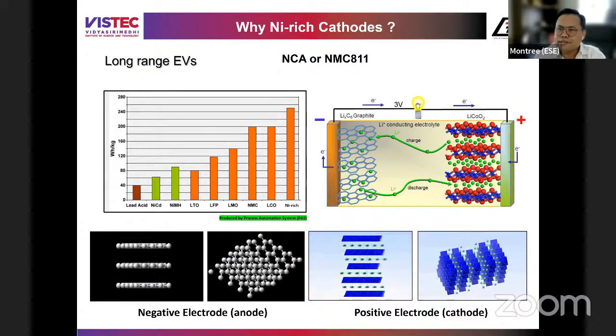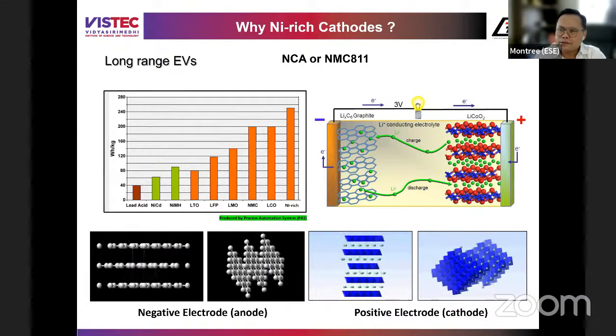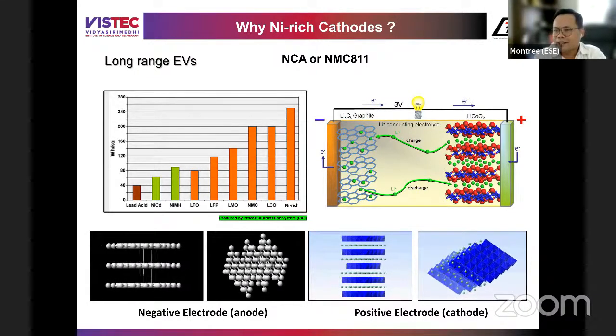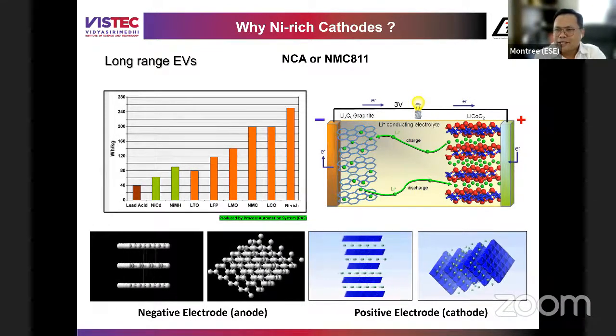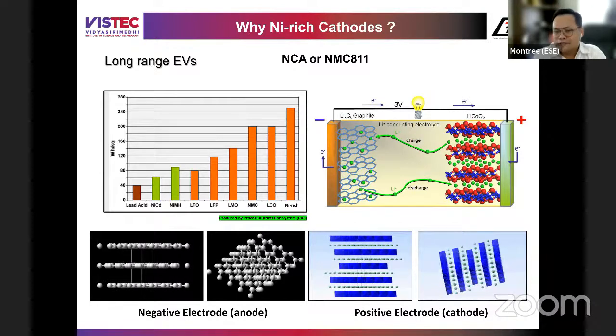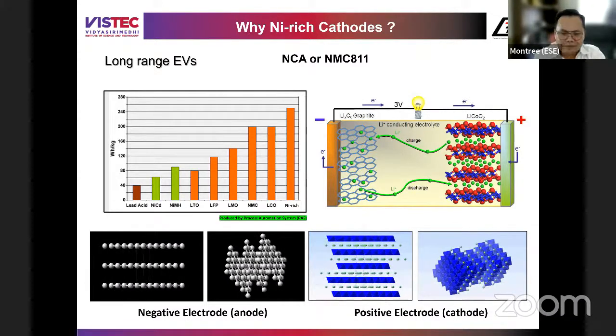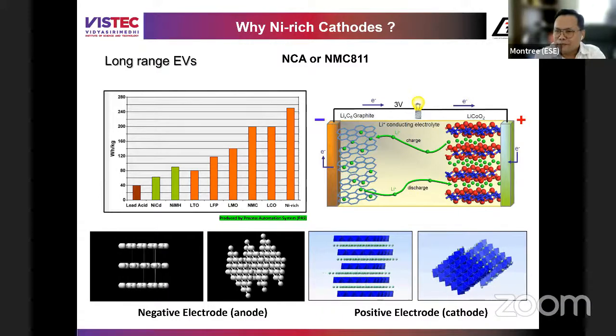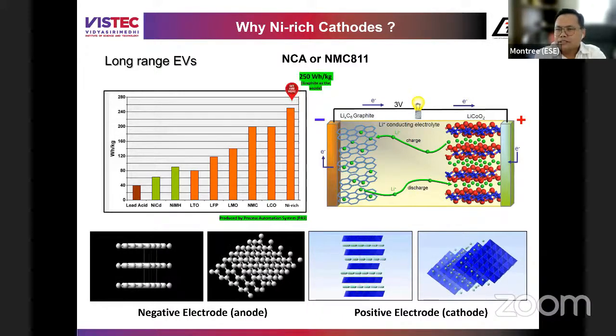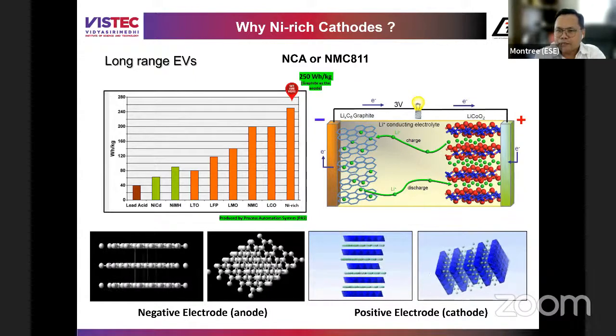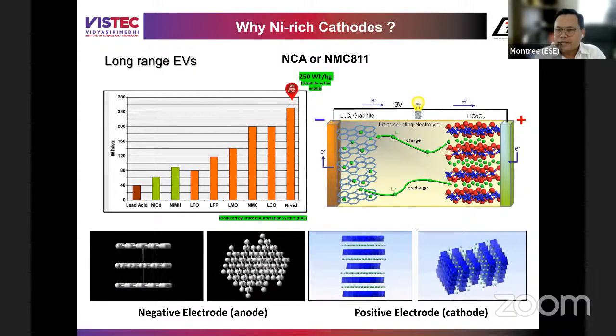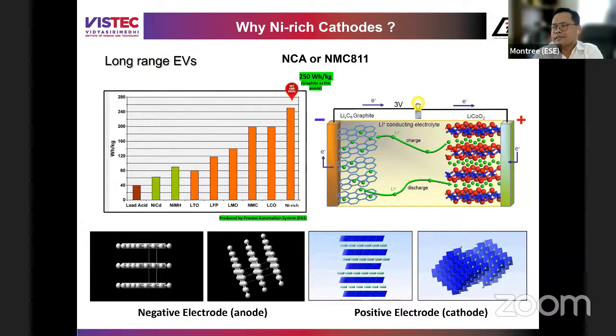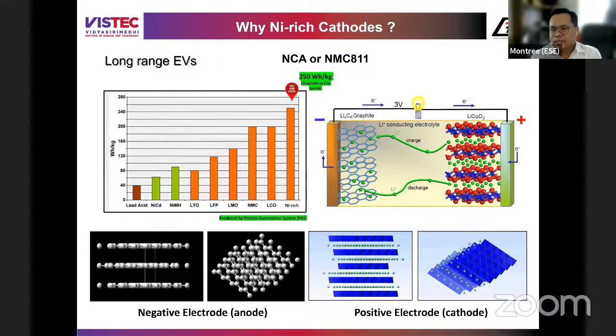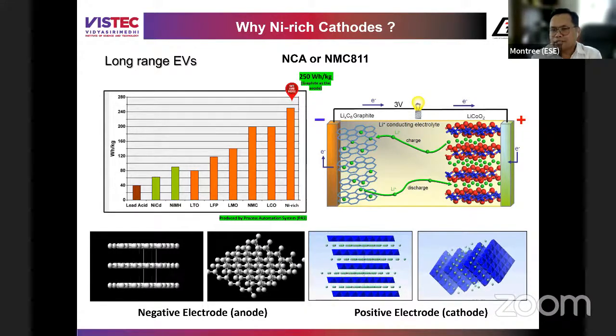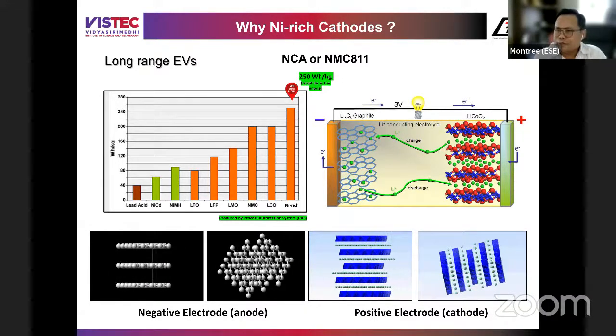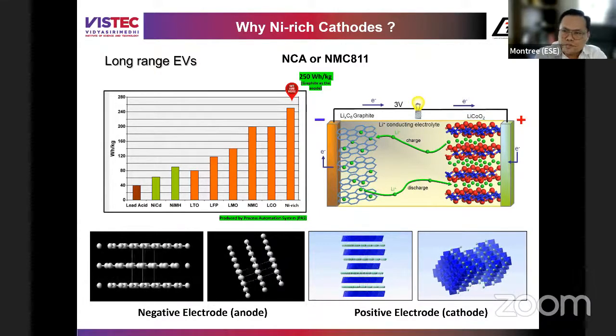right? 811 means 80% nickel, 10% manganese, and 10% cobalt. Cobalt is quite expensive, but right now, if you look at the stock, nickel price has become higher and higher, right? That is because of the demand of electric vehicles. And lovely, if we use graphite at the anode, coupled with NMC or NCA, it can have 250 watt hour per kilogram. That is the best energy density so far that we can achieve from lithium-ion batteries when we use graphite.